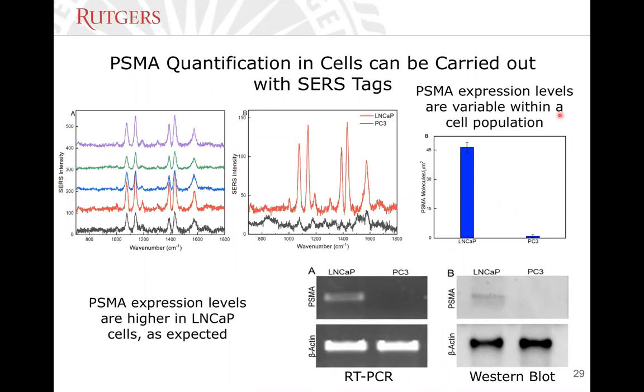What we also found is that we could determine the density of these biomarkers on individual cells. And we found out that LNCaP cells express about 45 PSMA molecules per square micron, compared to PC3, which is less than 5 molecules per square micron. So this is very interesting because now if we're able to have different cells at different stages of disease, we can actually quantify the progression of the disease by looking at just one cell or a small population of cells, by looking at the density of these PSMA molecules.